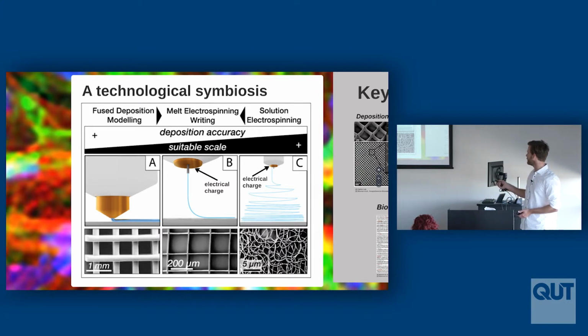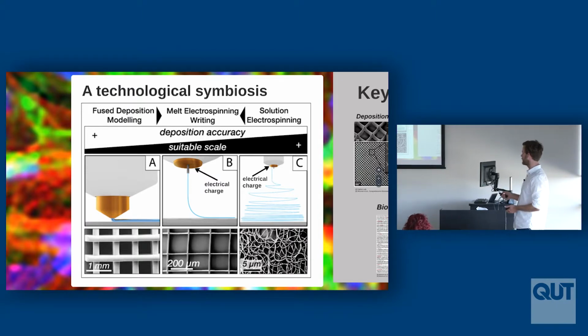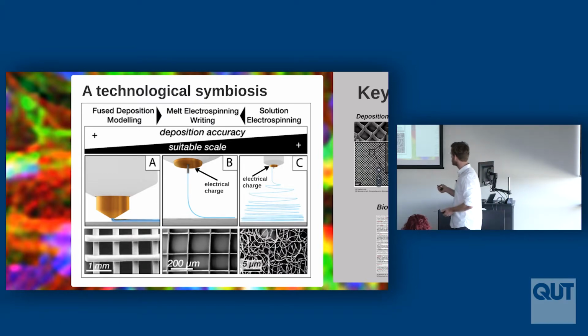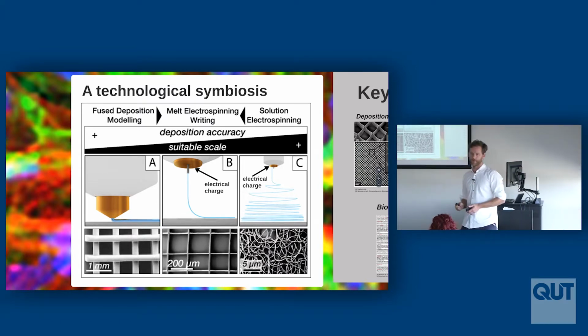On the other hand, we have fibers created with electrospinning. It's a very old technique where you apply electrical force to a viscous polymer, and then the polymer travels towards the collector but starts buckling really heavily due to the electrostatic force and ends up in randomized meshes. Interestingly, if you compare this side and this side, we have ordered structures here, but on a very large scale, and we have very randomized structures here, but with very small dimensions. Melt electrospinning writing is a combination of both.